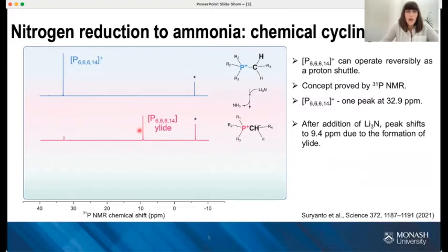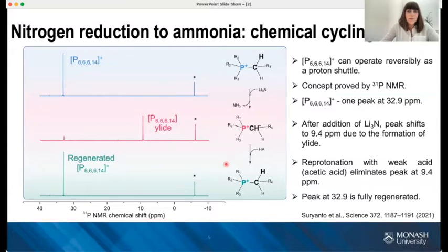produced here. So okay, we got half of the success, but the full success is to recycle that, so to reprotonate that ylide. And in order to achieve that, we added a weak acid. In this case, we added acetic acid to simulate reprotonation of that ylide, and that was successfully achieved, as you can see here. The peak at 9.4 fully disappeared, and the peak at 33 ppm was fully regenerated. And to be sure that this actually works, we repeated that 3 times, and every single time we got exactly the same results. So yes, that works. It can work as a proton shuttle.